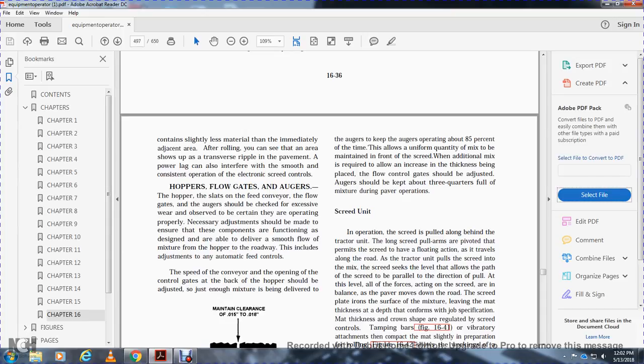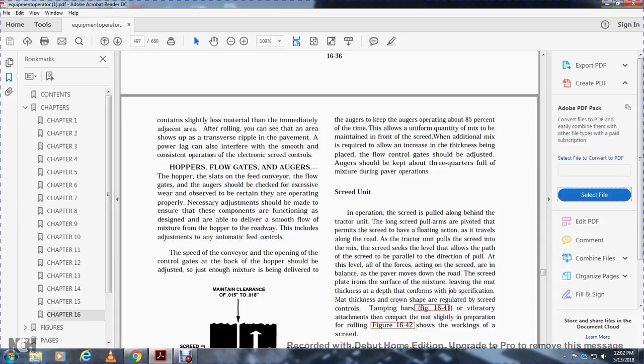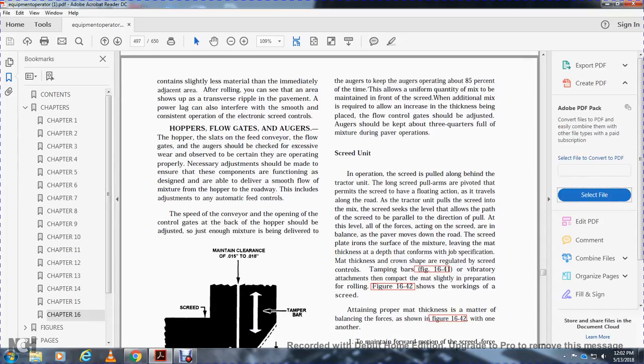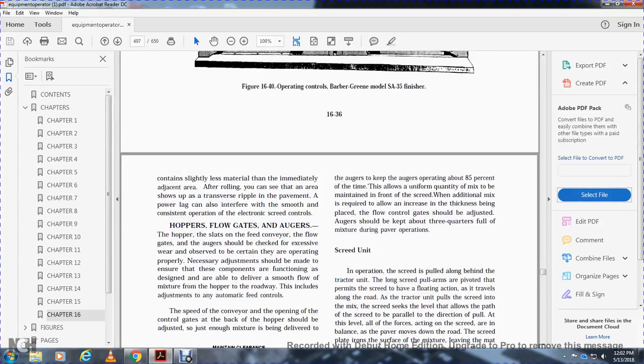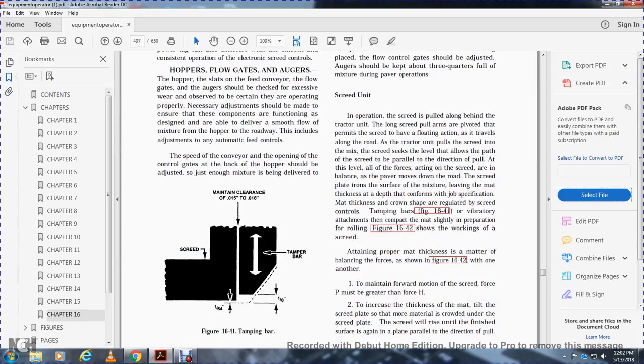Hopper, flow gates, and augers. The hopper slats, feeder conveyor, flow gates, and augers should be checked for excessive wear. If observed, corrective adjustments should be made to ensure components function as designed to drive a smooth flow of mixture from the hopper to the roadway. This includes adjustment of automatic feed controls. Flow control gates at the back of the hopper should be adjusted just enough to ensure material is delivered to the augers. Keep the augers operating at 85% of capacity to allow a uniform quantity of mix to maintain flow to the screed. The additional mix required to increase mat thickness is controlled by adjusting the flow control gates.